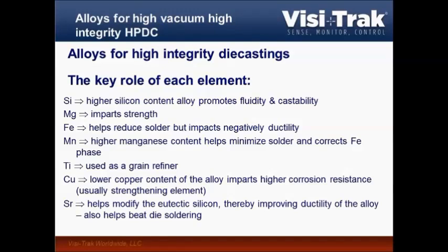Copper is simply kept low because at those low levels it's not used as a strengthening element like in other alloys. It really is just a problem for corrosion resistance. And strontium, as mentioned before, is used for modifying the eutectic silicon, or in higher levels in the Mercalloys to beat die soldering.